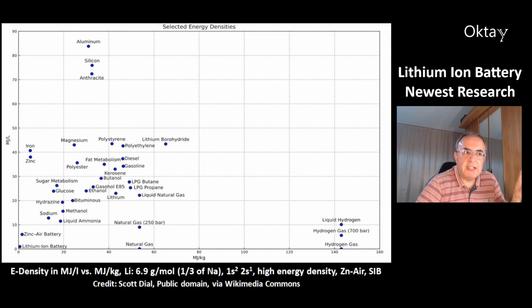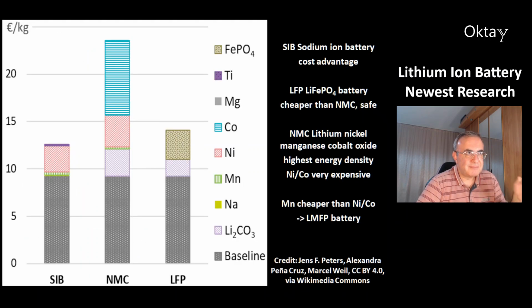Lithium-ion battery is known for its high energy density. Other technologies are the zinc-air battery and the sodium-ion battery. This is a comparison of these 3 technologies. At the left, that's the sodium-ion battery. It has a cost advantage, especially recently because lithium prices went up. The sodium-ion battery does not contain lithium. In the middle, that's the NMC battery. That's nickel, manganese, cobalt. It has the advantage of the highest energy density. However, the elements, as you can see, nickel and cobalt, are very expensive.